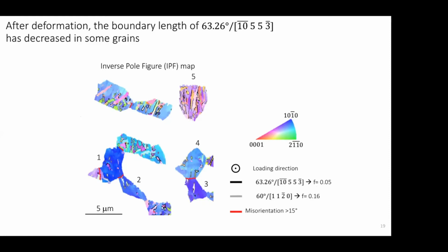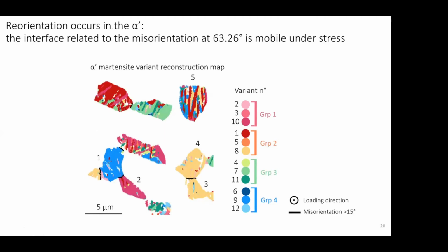But to have a clearer view of what we have after deformation, we also did the reconstruction of the variants, and you have the results here. So it's easy to say that the microstructure has significantly changed, and more especially, we have 2 extreme cases. The first one in grain 1, 2, 3, 4, where a single variant remains after deformation. And by contrast, in grain 5, we can see that all the variants remain in quite equal proportion.